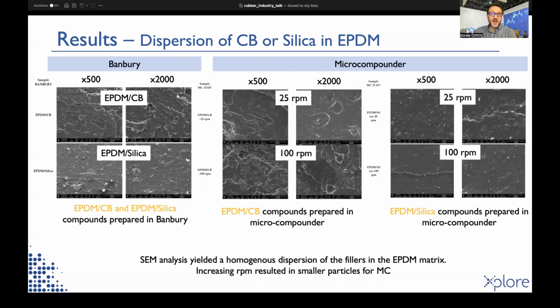We also conducted scanning electron microscopy analysis in order to further investigate the dispersion of the fillers in the matrix. The analysis showed a homogeneous dispersion of the fillers in the EPDM matrix when both mixing methods were applied. As can be seen in the figures, carbon black dispersed homogeneously in the matrix independent of the sample preparation method. On the other hand, agglomerated silica particles were obtained compared to carbon black due to the challenging dispersion of silica in EPDM. For EPDM silica compounds prepared in Banbury, silica dispersion was found to be coarser.